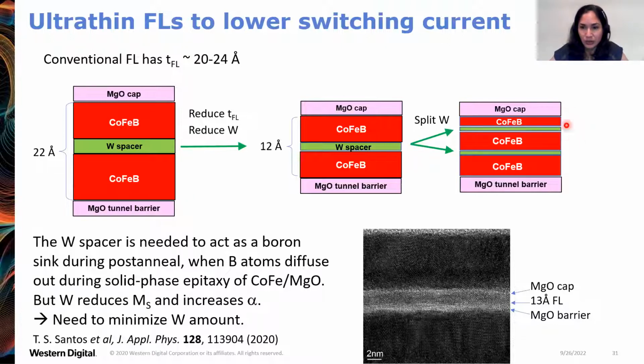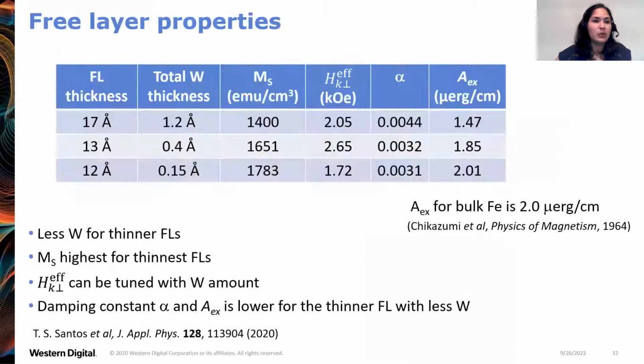So still, this is, for example, a 12 angstrom free layer. And here in this cross section, I'm showing a 13 angstrom free layer with the MgO barrier at the bottom and the MgO cap at the top. So we proceeded to use this type of free layer design with these two tungsten spacers, and we made a free layer thickness ladder. The thickest free layer in our study was 17 angstroms, and then we thinned down to 13 angstroms and then 12 angstroms. By thinning down the free layer, we reduced how much tungsten was necessary to keep perpendicular anisotropy of the free layer. By taking out a lot of tungsten, we increased substantially the saturation magnetization.